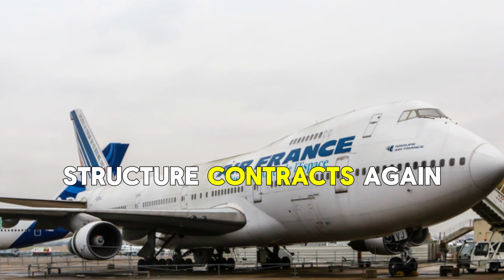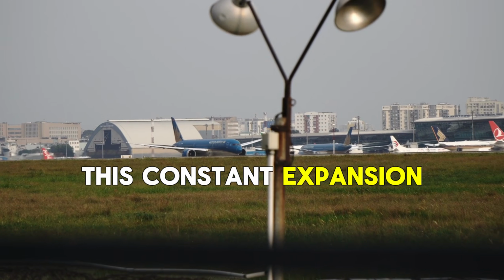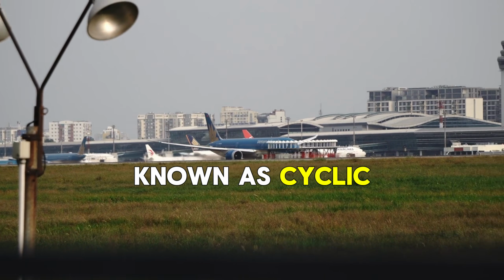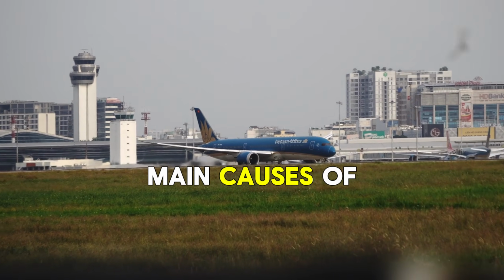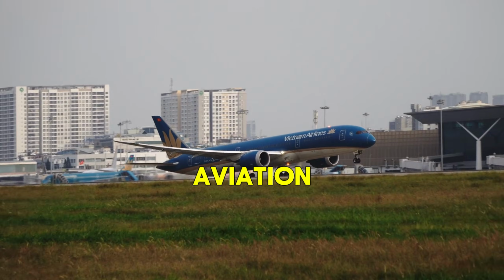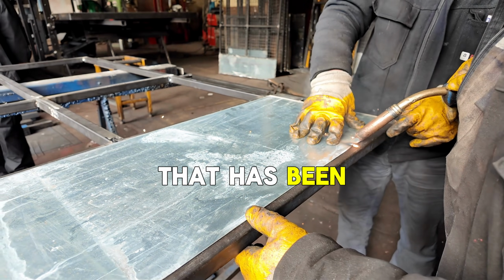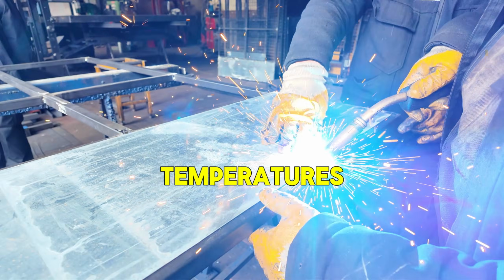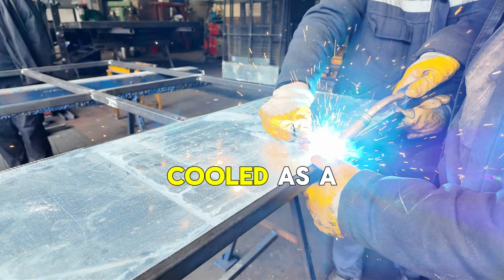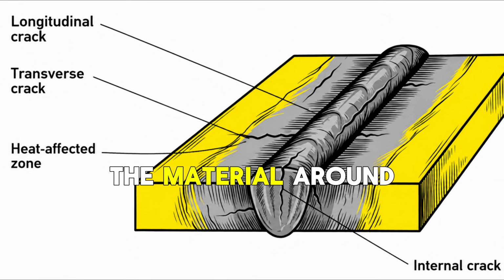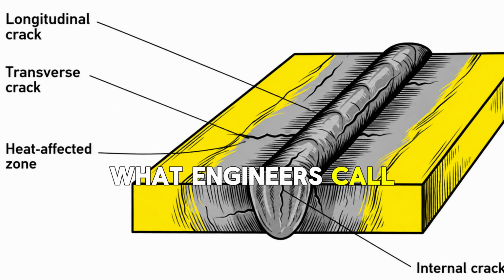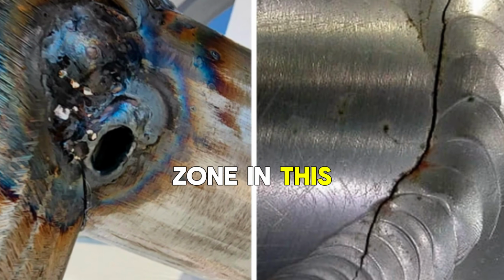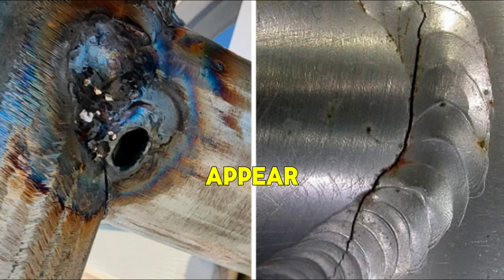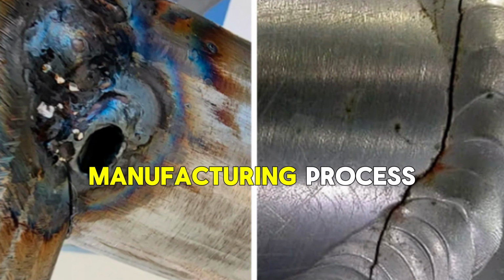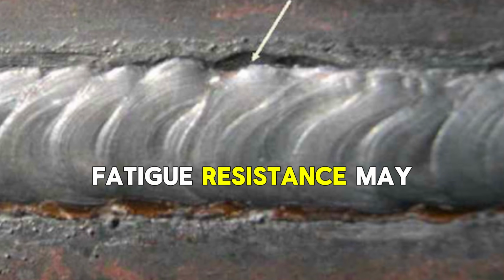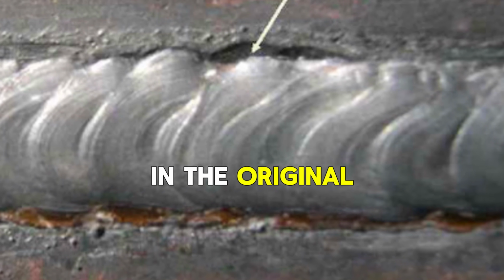The structure contracts again. This constant expansion and contraction is known as cyclic fatigue, one of the main causes of structural failure in aviation. A welded joint is an area that has been exposed to extremely high temperatures and then rapidly cooled. As a result, the material around the weld forms what engineers call a heat-affected zone. In this region, residual stresses can appear, and depending on the alloy and manufacturing process, fatigue resistance may become lower than in the original metal.